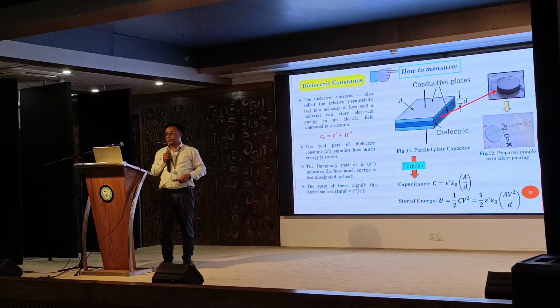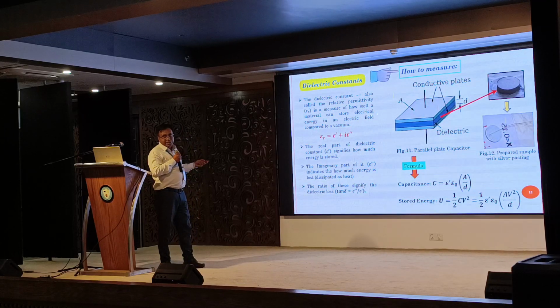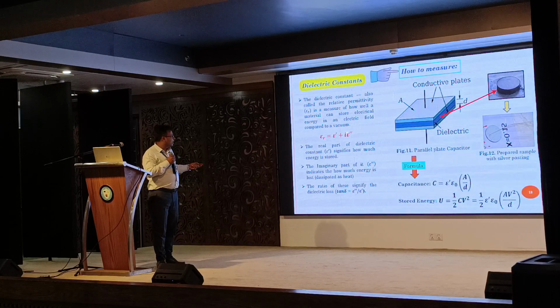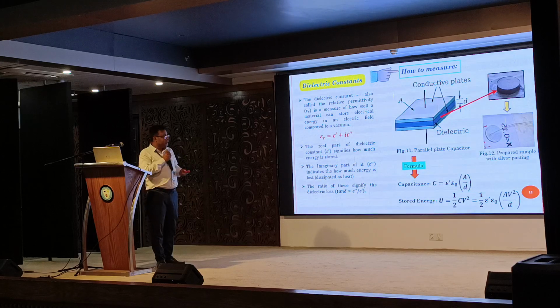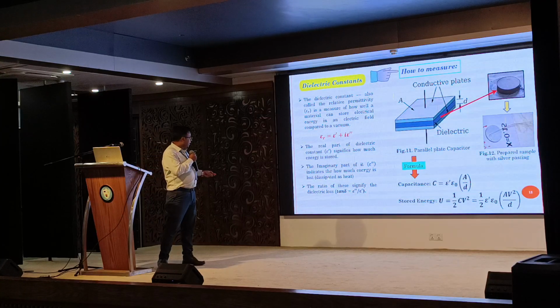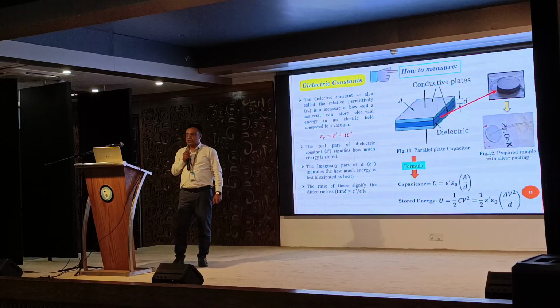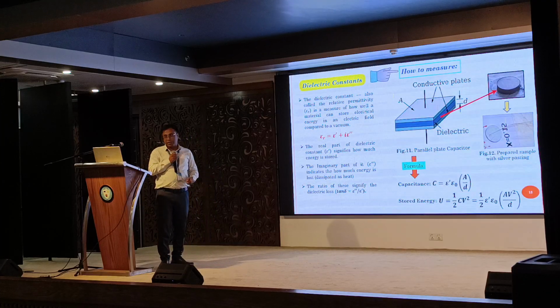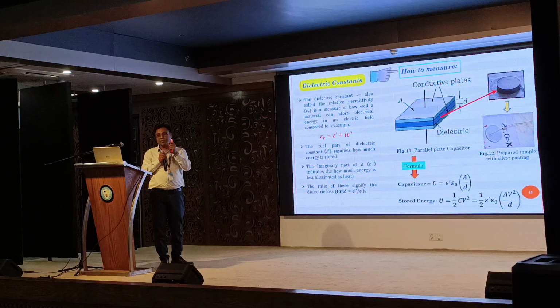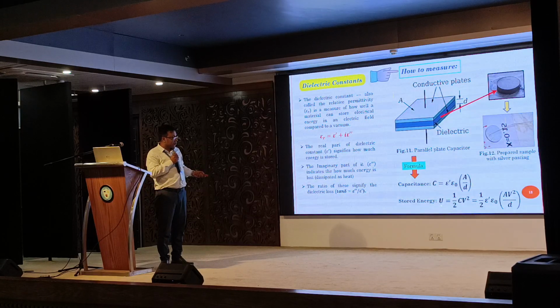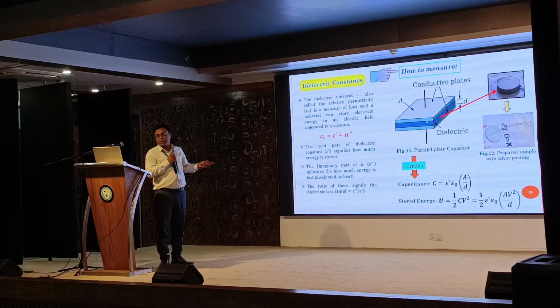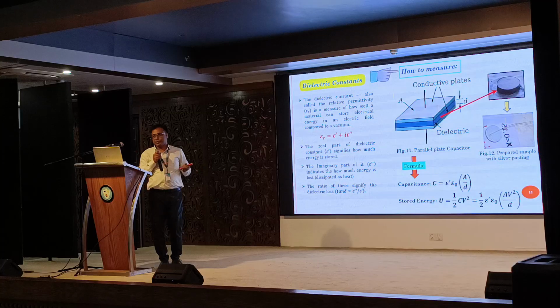You can measure the dielectric constant, and from the dielectric constant we find two parts. One is the real part, another is the imaginary part. The real part shows the energy stored inside the materials, and the imaginary part shows how much energy is lost inside the materials. This is also important for application, because you are applying energy but energy is being lost. So this part is also important. We have to focus on how much is lost, and we have to count it. Finally, stored energy we can calculate from this formula, U equals half C V squared, where C we can measure by the parallel plate capacitor method. This is a very easy experiment.